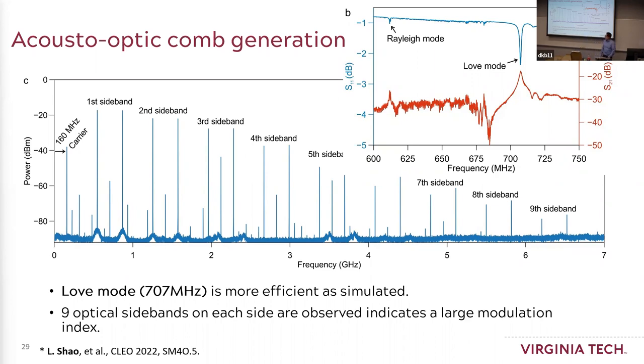The second thing is that we usually characterize how efficient the modulation is by seeing how many sidebands it can generate. With this acoustic cavity enhanced modulation, we can generate up to about nine sidebands, which indicates we can achieve over several pi of modulation. I also want to mention that these equally spaced frequency lines, in the optical domain, are called optical frequency combs, which are very useful in optical spectroscopy and in detecting chemicals and other things.